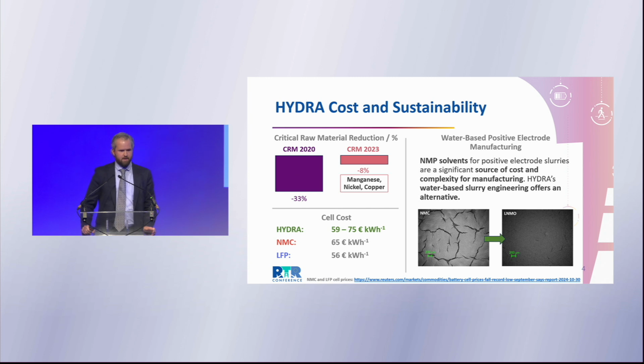The picture on the left shows a more traditional material, NMC, when cast with a water-based slurry, and we can see it's got these large cracks that come from the corrosion process, releasing gas and just kind of tearing the coating to pieces. And compared that with our slurry-engineered LNMO result, where we see nice, homogeneous, good coatings, indicating that with these slurry engineering methods that we developed in Hydra, this is indeed possible to do. And we see the benefits in the bottom left of the slide there of reducing the reliance on critical raw materials, improving the manufacturing process, with Hydra being able to achieve a cell cost between 59 and 75 euros per kilowatt hour, which is comparable with current NMC and LFP prices.